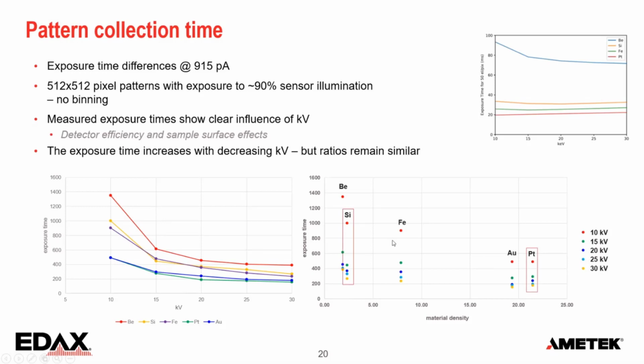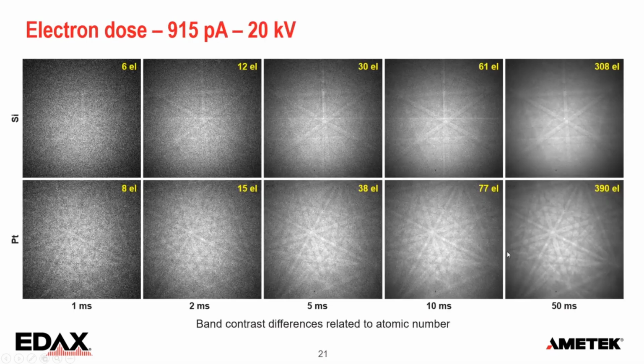Now, let's take a look at what the patterns actually look like. Silicon, platinum. This is, again, the same conditions that we made all these simulations for. On the left, 1 millisecond exposure. For silicon, on average, we have 6 electrons. For platinum, we have 8. And you can just make out the pattern on the silicon. Platinum is a bit easier. So that's the background to band ratio that really makes this so much nicer.